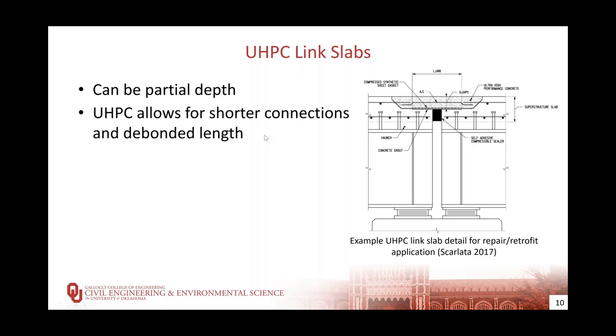It takes less time to remove the concrete, which has some potential benefits as well. UHPC allows for shorter connections and debonded length, both in the splices into existing reinforcement, as well as the debonded zone within the slab. And that can allow us to go from needing to debond 5% of the span for conventional concrete link slabs, plus the embedment on each end to make the splice, to a 2 to 3 foot total link slab using UHPC.